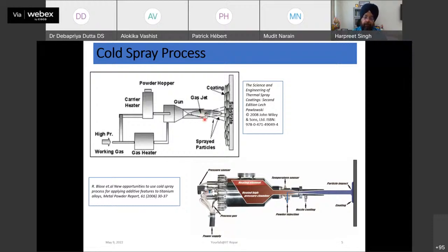Now this is one thing. Now why am I accelerating this gas so much? Because I want to propel my powder particles at very high velocities, so that they can move at supersonic velocities, and then they can strike on the surface where they will stick as the layer. So that's what we are doing here. We are taking the powder particles and heating them just to remove the moisture. It's not that we are melting them or something like that, as we used to do in thermal spray. So here the beauty is that we are doing everything in solid state.